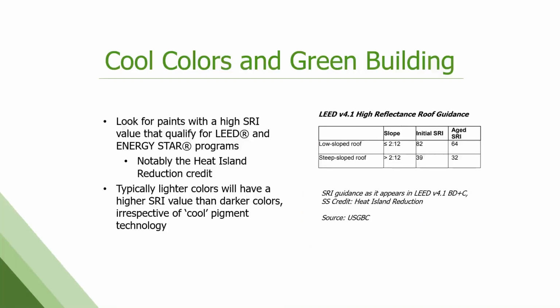So, right, the higher the SRI, the better, but that's somewhat dependent on your color as well. Lighter colors obviously are going to have a higher SRI than dark colors, even with cool pigmentation. And you can see there the new LEED guidelines for low slope and steep slope. Low slope is pretty high, has to have an initial SRI of 82. That really limits you pretty much to whites, maybe some very pale tans and grays. Steep slope, you have a little bit more room to work with. An initial SRI of 39 is going to give you some medium colors. It used to be 29 for LEED.